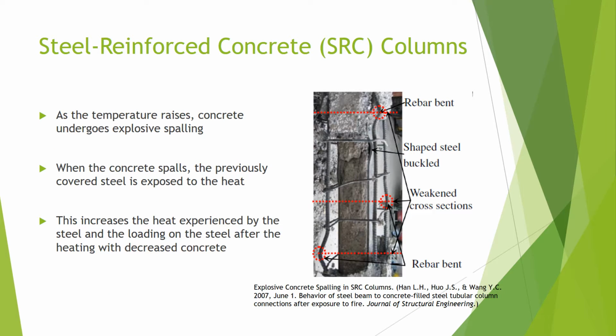As the temperature rises, concrete undergoes explosive spalling. When the concrete spalls, the previously covered steel is exposed to the heat. This increases the heat experienced by the steel and the loading on the steel after the heating with the decreased concrete. The figure shows the bent rebar, the weakened cross-section, and the buckled steel.